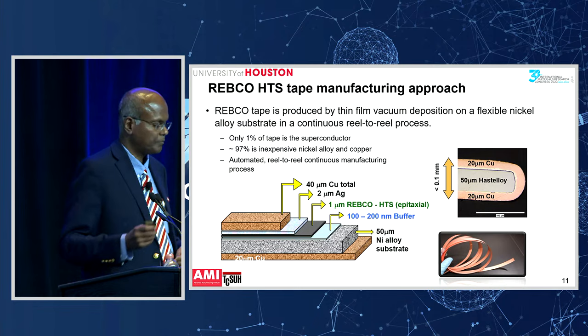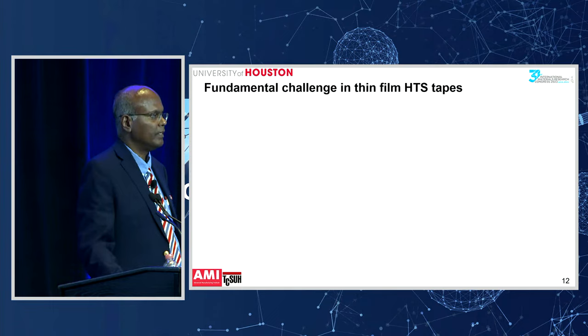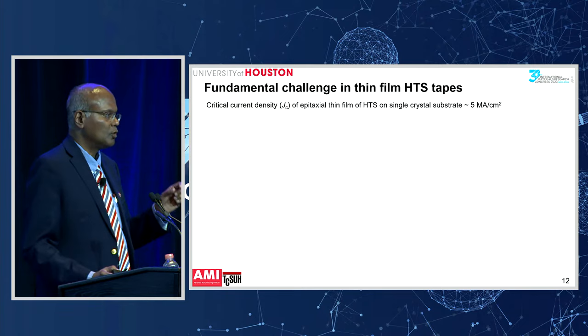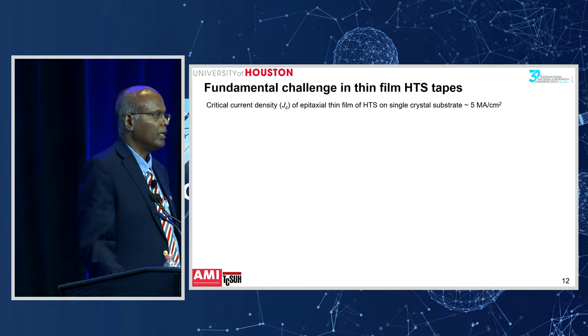However, there was a fundamental challenge with making these thin film superconducting tapes. Because if you deposit the superconductor as a thin film on a single crystal substrate, basically an epitaxial film, you can get a high current carrying capacity, or critical current density, of 5 million amperes per square centimeter. Just as a comparison, copper can only handle 100 to 1,000 amperes per square centimeter. So you can see the superconducting film itself can carry 5 million amperes per square centimeter.